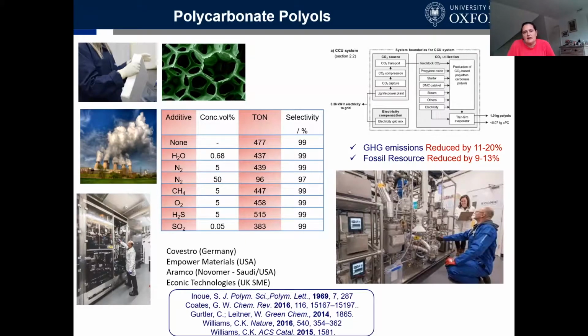And it's worth saying that that life cycle analysis conducted in Aachen by Gürtler and Leitner and so on, and Bardow, of course, was conducted on a polymer that didn't have very much CO2 in its backbone. It only had about 10% CO2. For various reasons, the catalysis that German group were using doesn't take much CO2 up. You will see later on in the talk that we can really improve upon that 10% and have up to 50% of the backbone of the polymer from CO2.